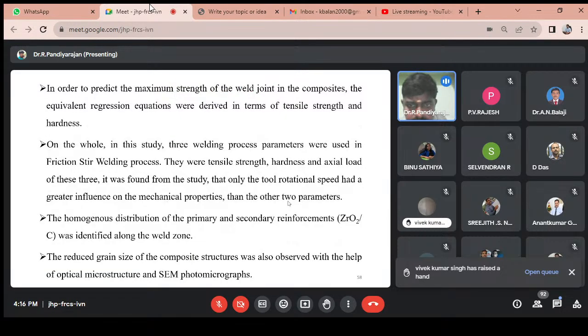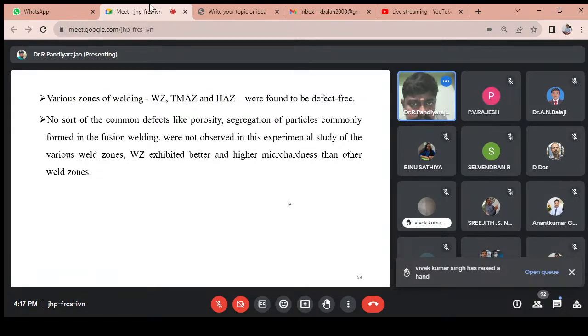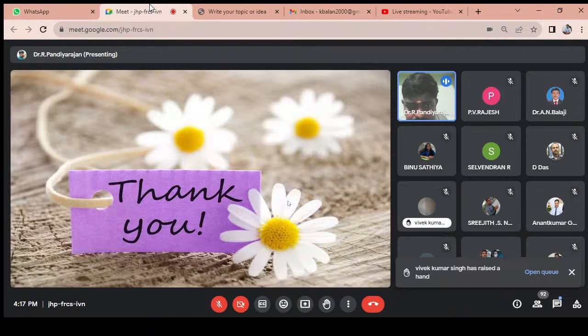Once we find the best weight percentage of the aluminum based composite material, we do the friction stir welding process parameter study, and we use an optimization technique to find the most influencing parameter. We also do metallurgical characterization of the weldments by using OM analysis in different zones, and the hardness survey is also done with the optimized process parameters. So, thank you.